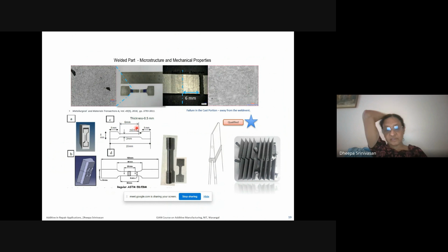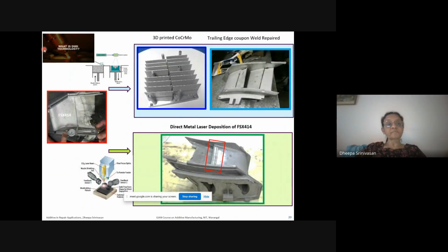But one of the things I wanted to share here is the big challenge again. Because it was a thin part that was welded, there are no well defined test techniques to qualify this particular joint, because typical test samples are quite bulky, as shown here in this example. So this is ASTM E8, and this is one of the smallest specimens. Obviously, I can't take it out of such a thin joint where I've joined it by a weld repair. So there is a big need for developing small scale testing and getting it qualified in order to accelerate the applications of using additive manufacturing for both new make, advanced designs and for repair solutions. So, I will leave you with this thought and move on to the next example.